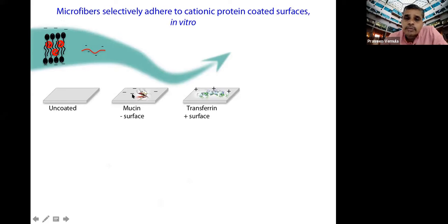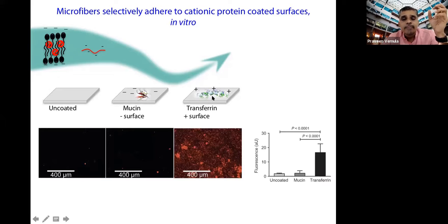As a control, we took mucin, which is in your healthy intestine, as the mucus has this mucin. So we coated that onto a plate. Then these fibers, which were encapsulated with the dyes, were incubated and washed extensively, and we measured the amount of fibers attached. As you can see, these fibers are completely attached to the transferrin protein, whereas they don't bind to the mucin protein at all, which is not very surprising, because you have anionic particles and a cationic protein, and they tend to bind.